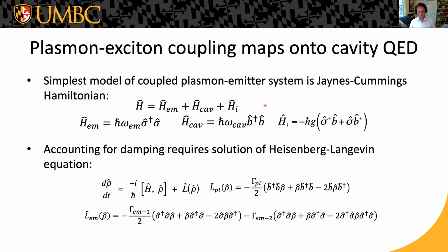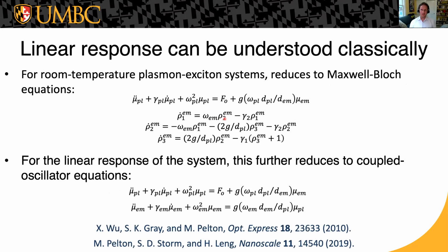And this is really just to show some of the level of theory that I'm going to use to either make predictions or describe our experimental results here. In some cases, with Stephen Gray, who I think is listening right now, we did fully quantum mechanical calculations in the Heisenberg-Langevin picture, the master equation picture, using Lindblad operators to describe the damping that's not incorporated in the Jaynes-Cummings model. But basically, for everything that you are going to get with plasmonics, especially at room temperature, this all reduces to a semi-classical situation, where you don't have to actually quantize the plasmon field. You can treat it classically using the Maxwell-Bloch equations, keeping the emitter, the exciton, or whatever system you're looking at as your two-level system.